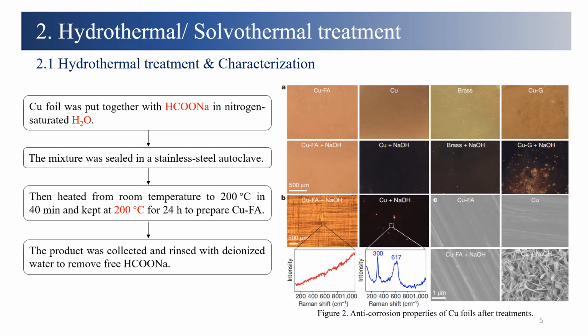The copper foil was put together with sodium formate in water, and the mixture solution was sealed in an autoclave, kept at 200 Celsius for 24 hours, and then collected as copper formate. We can see the result intuitively in Figure 2.